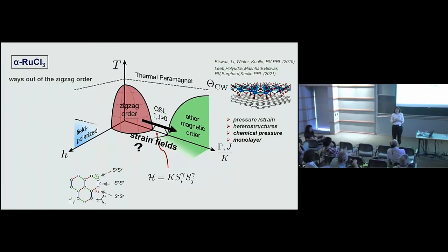Sure. We all don't like disorder, but can you estimate how much iodine you would need to reach the negative pressure range? Is it 1% or 10% to reach the preferable ruthenium trichloride lattice distances? Just when you compare the lattice constants of the two materials. I haven't done the exercise. I should look into that. There are materials that can experimentally show that they can compensate doping by pressure and get back the old phase diagram. So sometimes you're lucky. You're right, I should look at these numbers. I cannot tell now.